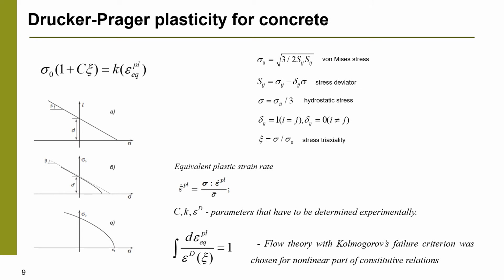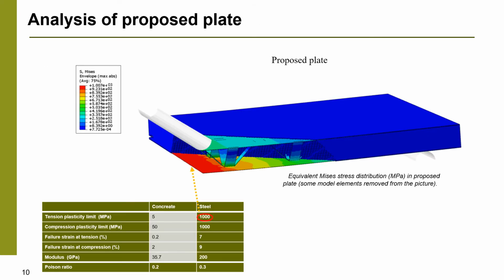It allows to consider the differences of yield strengths for the tension and compression, and Kolmogorov failure criterion was chosen to consider equivalent plastic strain accumulation. For the proposed plate, we use the identical modeling approach. On this slide, the one with stress distribution in the metallic component is presented.